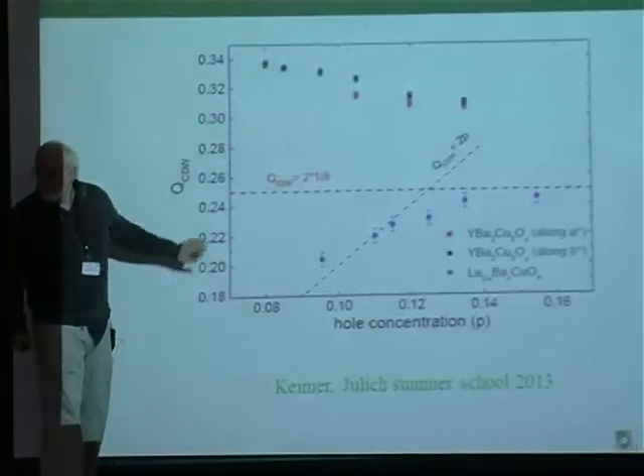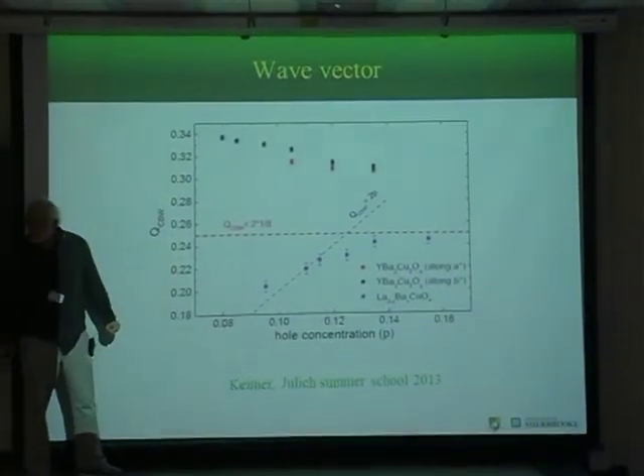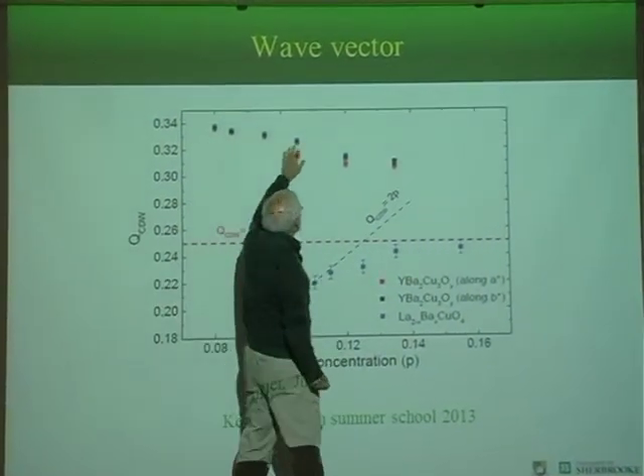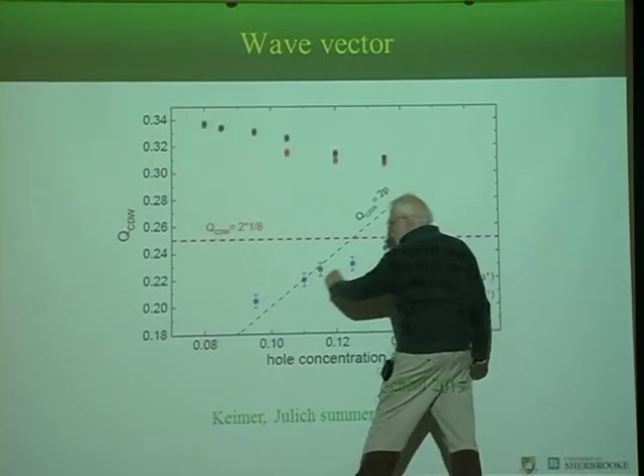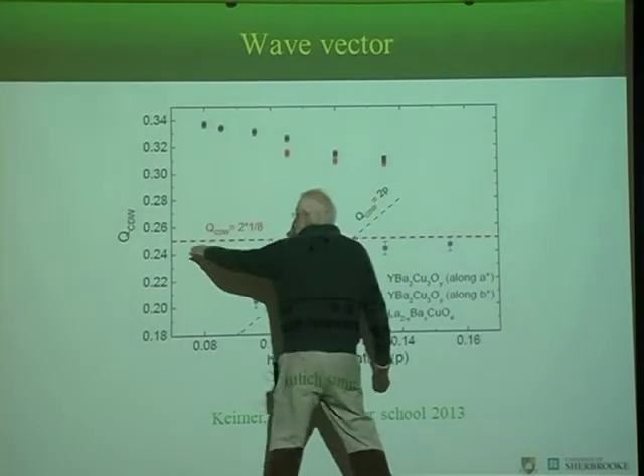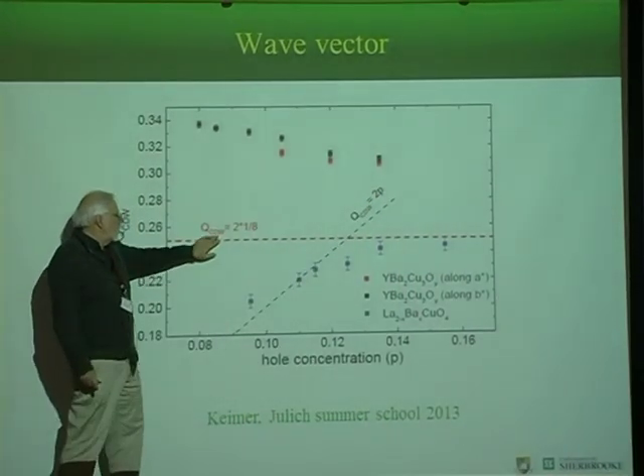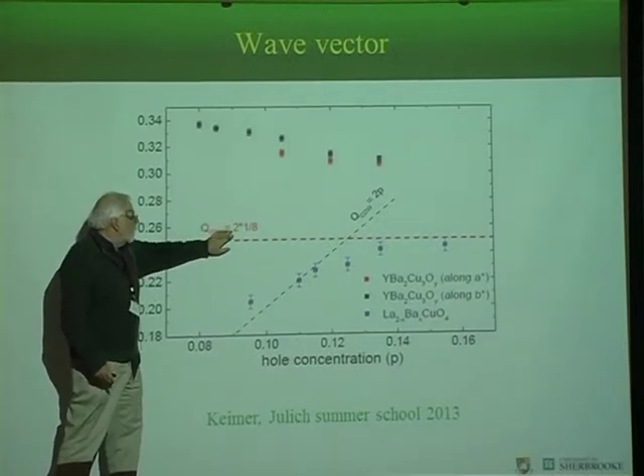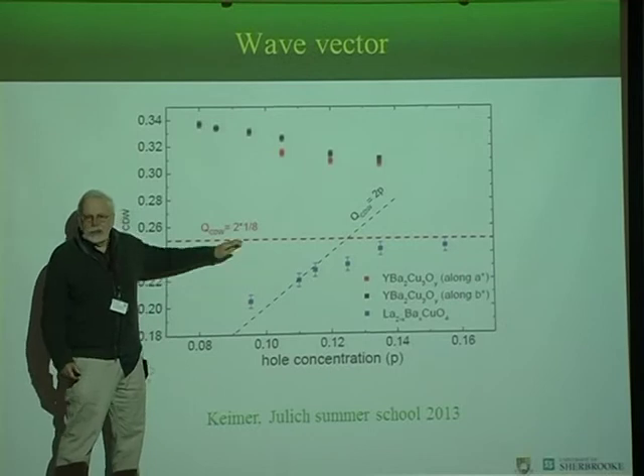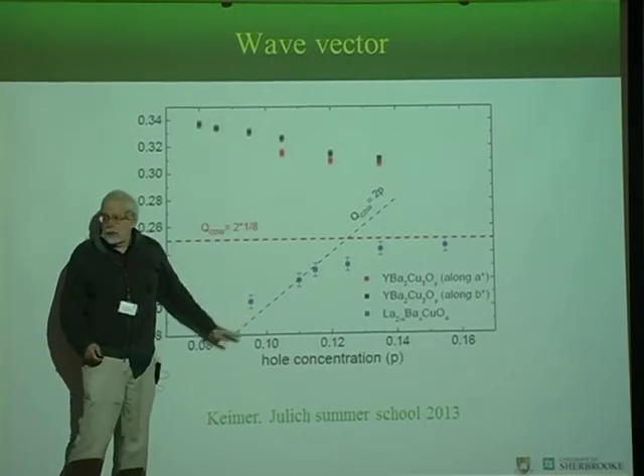Yes? So what is the structure of the CDW in terms of the Q vector, and does it change as a function of doping and temperature and so on? Yeah, very good question. The Q vector is here, as a function of hole concentration. You see that it changes a little bit, and it's different from LBCO. LBCO is here. And this is what you would expect from naive arguments, from the stripe discussions that were going on for a long time, it would be 2 times 1/8. So it is not quite this, you see.